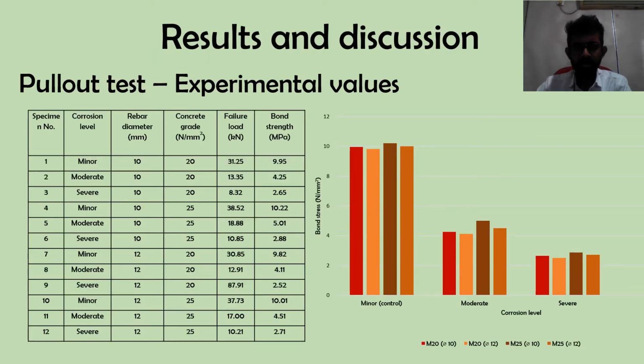Results and discussion. Starting with the experimental values of the pull-out test, it can be seen from the graph that the bond stress relevant to the moderate corrosion levels is reduced by about 55% and severe corrosion levels are reduced by about 70% when compared to the no corrosion stage. But the reduction of bond strength is less for the specimens with grade 25 concrete compared to grade 20 concrete.